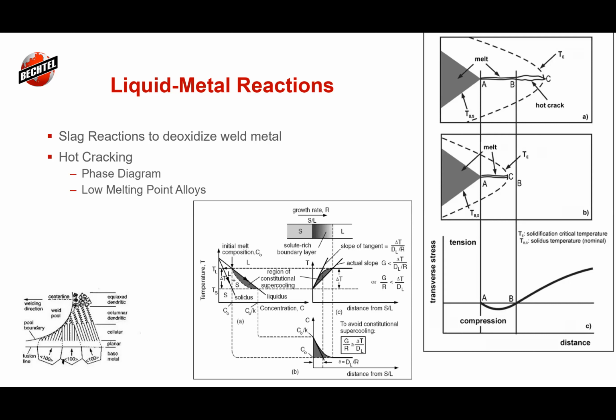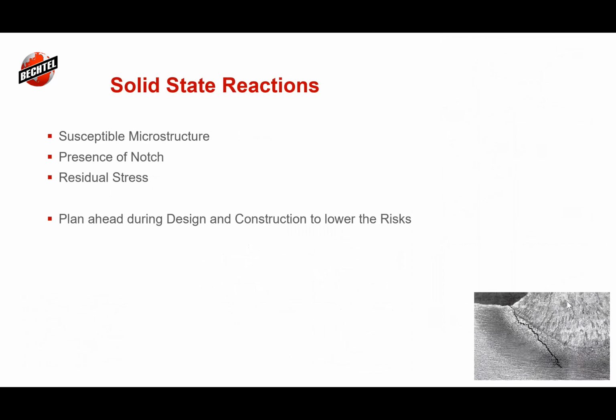And so joint design can have a huge effect, not only obviously on the heat input, because if you have a wider joint, you can have a tendency to go to higher heat input. And that's why we need to step that heat input down and do split bead passes, or be able to distribute that heat out, so it's not as focused on the heat affected zone and has a tendency to shrink and pull together. Oh, that's a really nice picture.